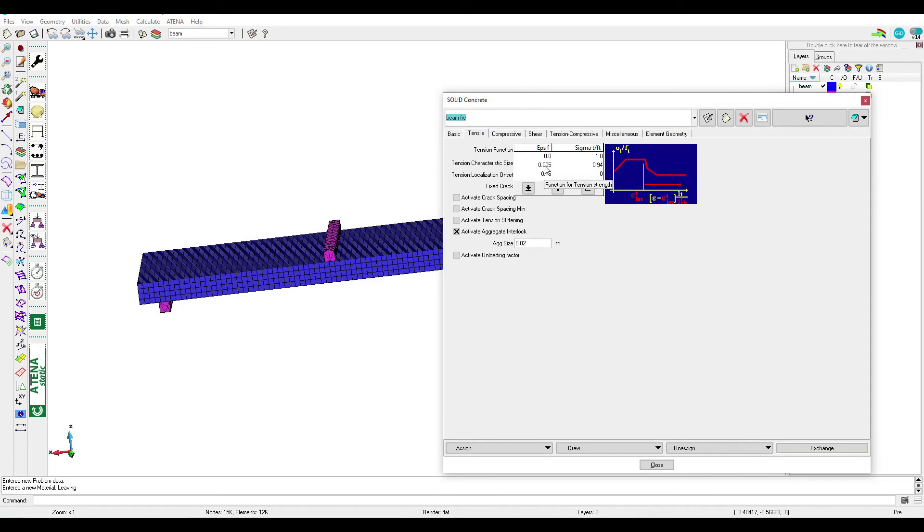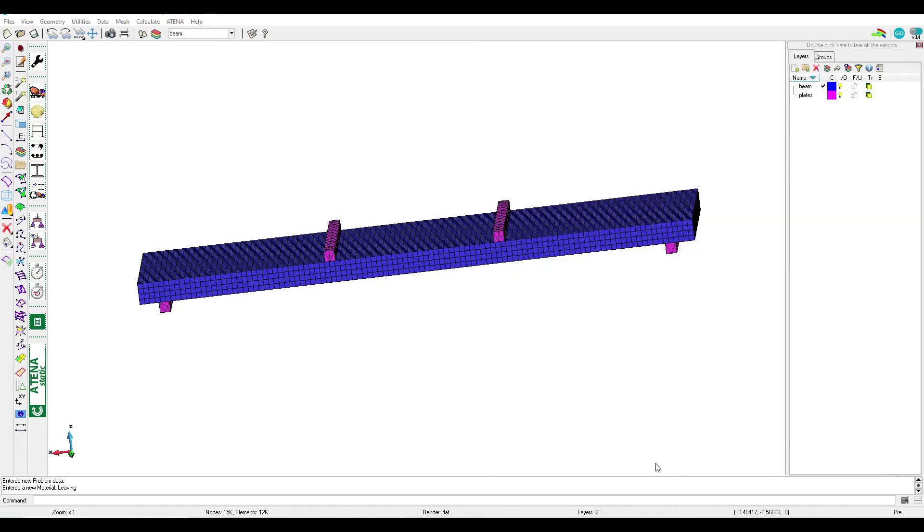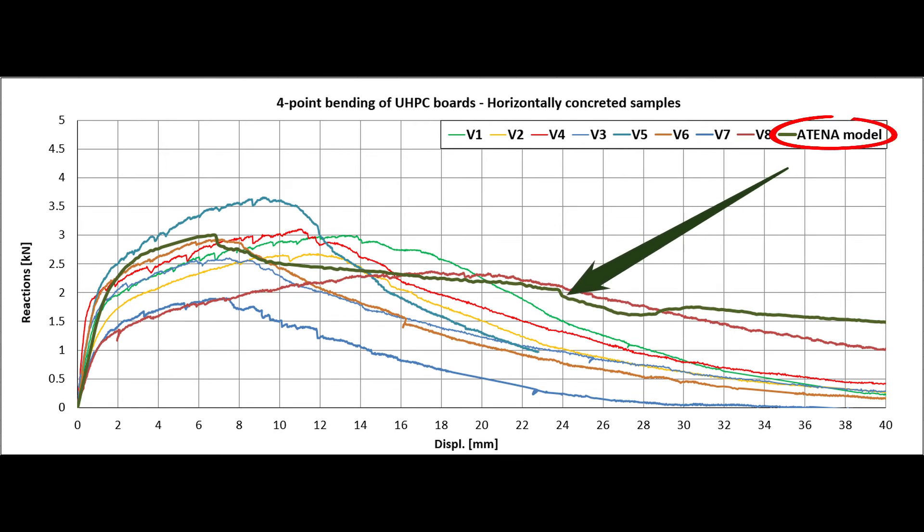We can go to material and make a smaller value and shift another value to 0.1 or keep it like this. Relative stress we calculated from previous steps, we can keep it like 0.25 to see in the beginning. By applying these values we will get this LD diagram in green color. Now it's better, but after the peak the softening part is still higher than the experiment.